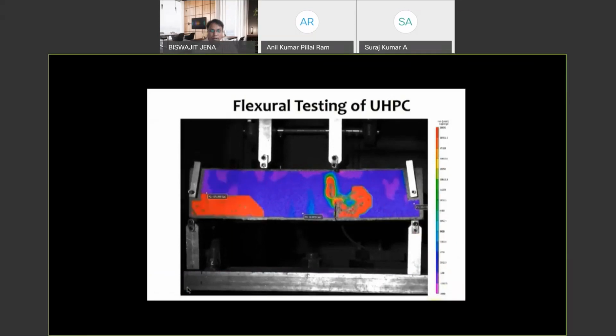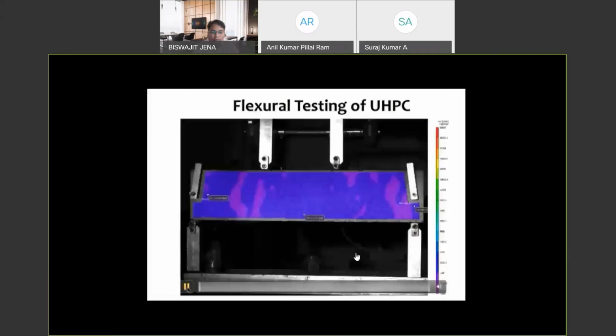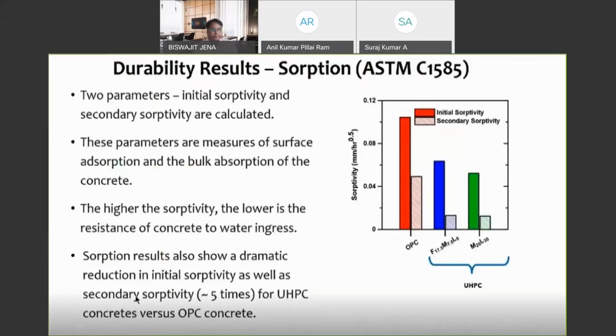When you start to see the red, can you see the crack here now? If you theoretically calculate the process zone as some value of strain, then you can quantify what the process zone is and how the process zone changes with load. You will see random cracking, and you will see extremely high strains at different locations.